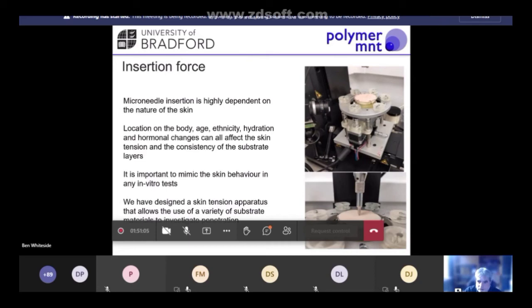So once we've verified how the materials buckle, we then want to do tests in our porcine models. Early on in the process we realized that the penetration behavior into skin is hugely dependent on the condition of the skin and also the tension within the skin. If you look at anyone you want to apply a microneedle treatment to, the skin is very different depending on the body location. Obviously, the skin on your upper arm or your thigh behaves much differently to the skin on your ankle, or somewhere where you don't have the same level of underlayer material. Age significantly affects the mechanical properties of skin. Ethnicity, the amount of hydration you have, hormonal changes, they can all affect skin tension and the consistency of the substrate underneath your skin. And we need to take that into account during our penetration tests.